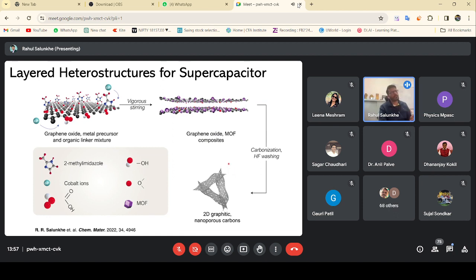In one more interesting approach, we try to develop this material into a two-dimensional form. In the two-dimensional form, we develop a graphene sheet, and on the graphene sheet, we link imidazole linkers, and on those imidazole linkers, we develop a cobalt-based MOF. So now we have one graphitic layer of graphene, and on top there is a cobalt-based MOF, and because of that, layered heterostructures can be generated. After carbonization and washing, we get 2D graphitic nanoporous carbon materials.